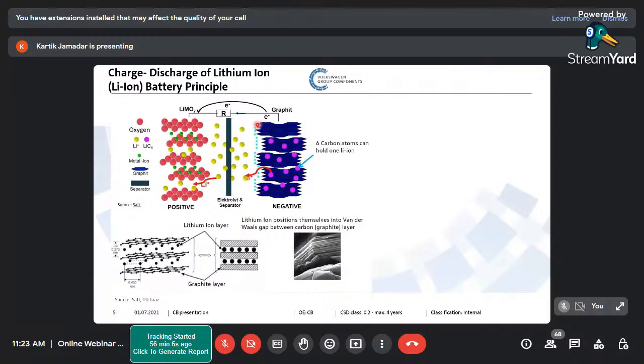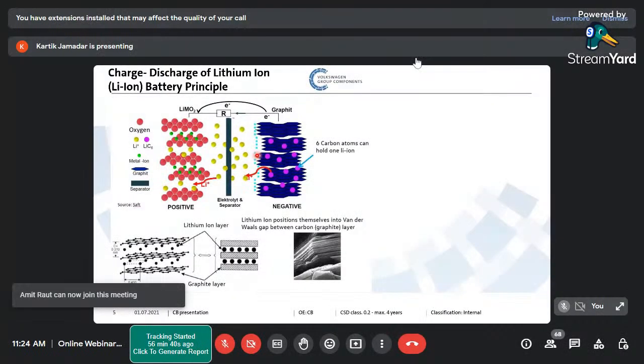In lithium ion technology, there is a protective layer which is formed on the graphite by the electrolyte. It is only formed one time, and we call it the solid electrolyte interface. It is a very important protective layer. Otherwise, graphite will deteriorate every cycle. But once that protective layer is formed, it does not get deteriorated. That protective layer is very important for the life cycle of the battery, and it starts deteriorating around 60 to 70 degrees centigrade. So that is the first effect. You will see that the life cycle of the battery goes down.